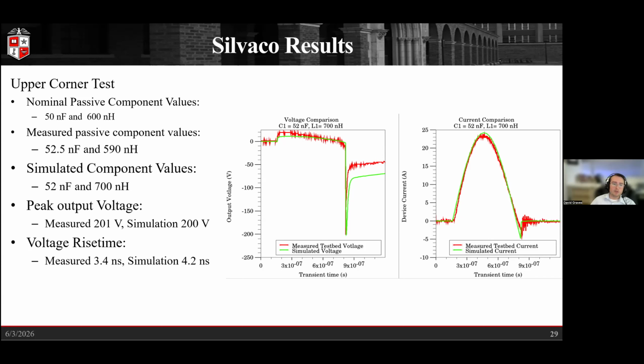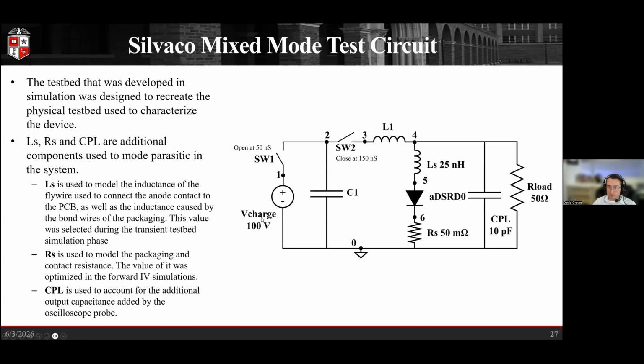Looking at the peak output voltage, we measured 201 volts, where our simulation was at 200 volts, and our measured rise time was 3.4 nanoseconds, where in simulation it was slightly longer at 4.2 nanoseconds. One of the things to mention with this when we're looking at our peak output voltages, these are not very impressive values on their own, being that we're only getting a gain of about 2x, being that we charge to 100 volts, as we are showing here.